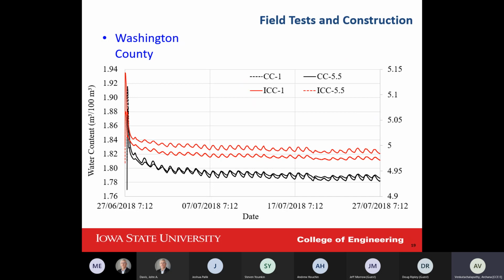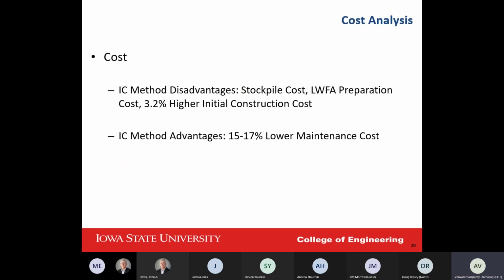Because the lightweight fine aggregates hold the water inside themselves. So they are placed in the concrete, and after the hydration is happening, they release the water out. The hydration is going on, but the porosity is higher, so they are capable of keeping more moisture in it. That's why the slab that we use with lightweight fine aggregate is more capable of holding water and staying more moist than the one which is dry. And that means, yes, we do have higher water content in the slabs that we use the internal curing in.